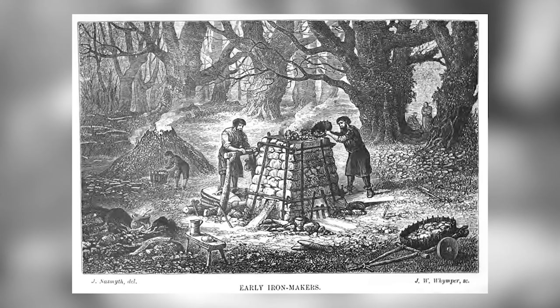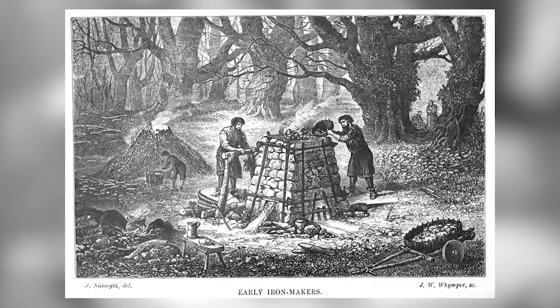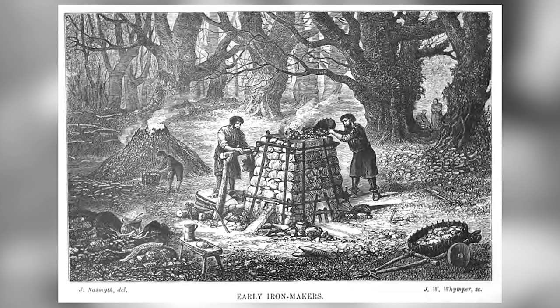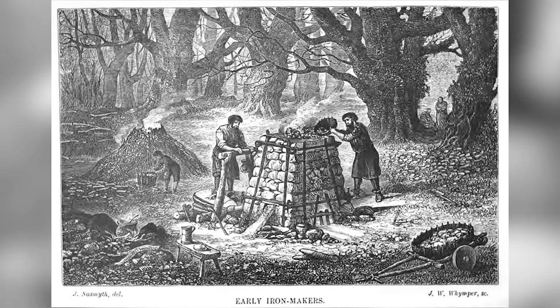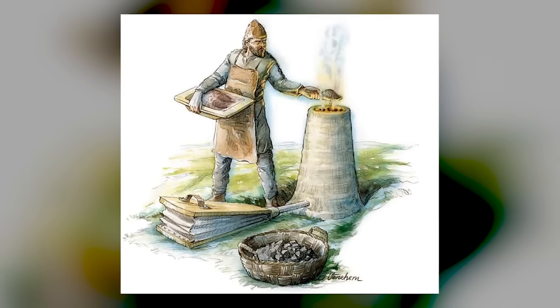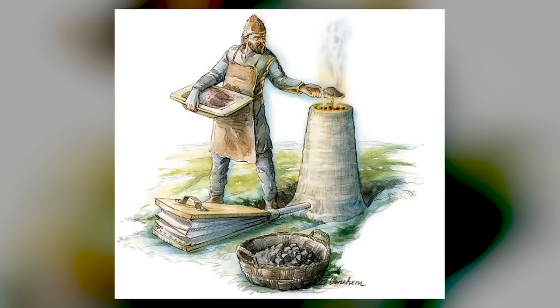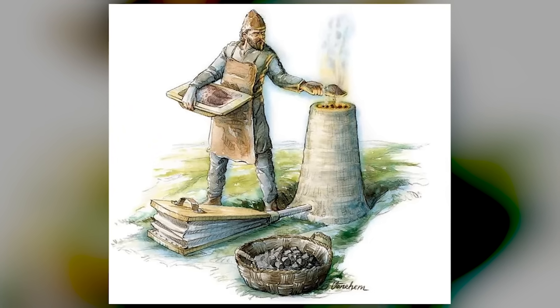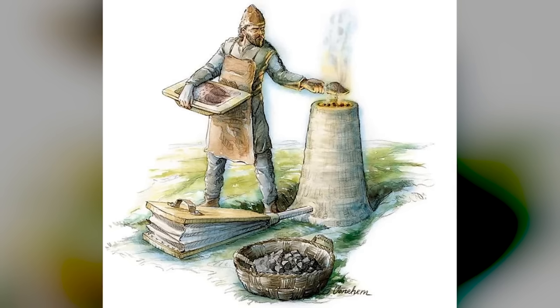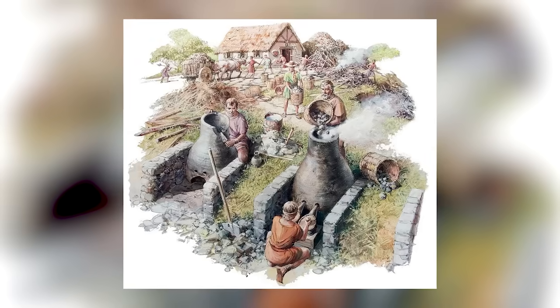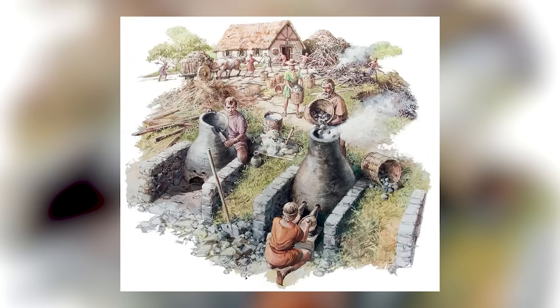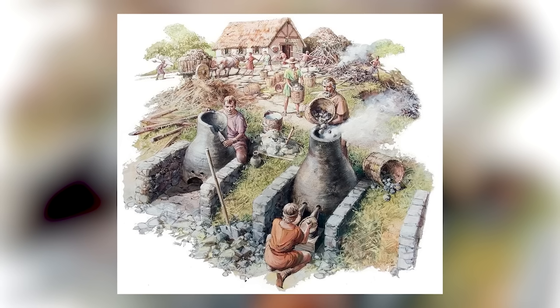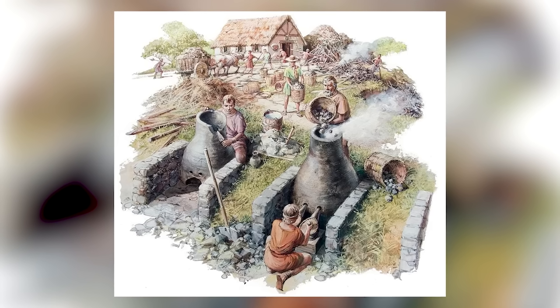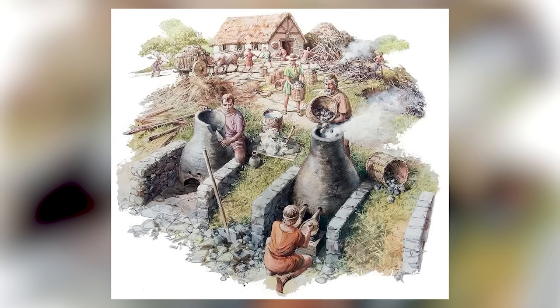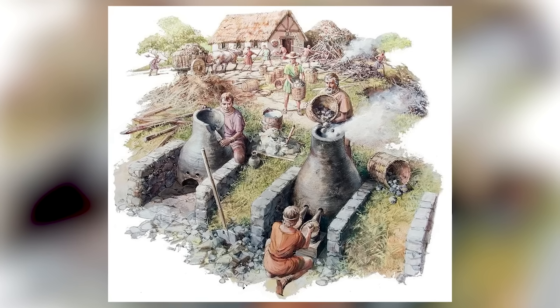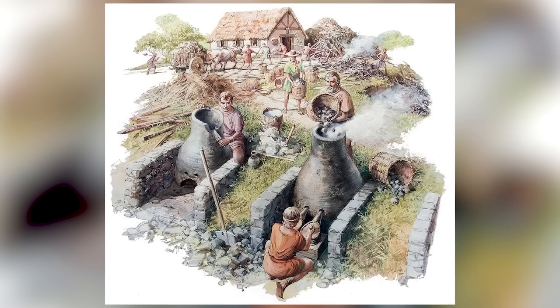As the charcoal burned, it produced carbon monoxide gas. This gas pulled oxygen away from the iron ore, leaving behind particles of pure metallic iron. But all the rocky impurities in the ore, the silica and other minerals, those did melt. They formed a glassy slag that dripped down through the furnace. The solid iron particles sank into this molten slag bath, clumping together at the bottom into a spongy mass called a bloom. After hours of work, the smith would crack open the furnace and pull out this incandescent blob. It looked more like volcanic rock than metal.